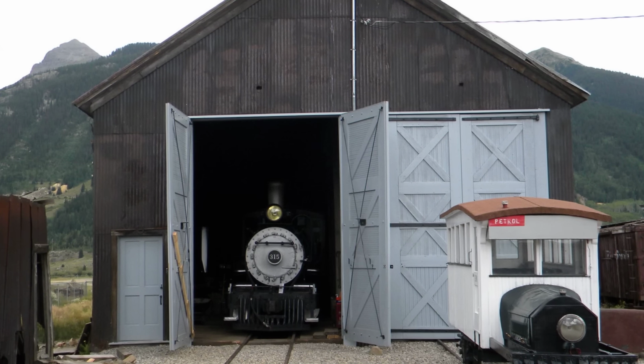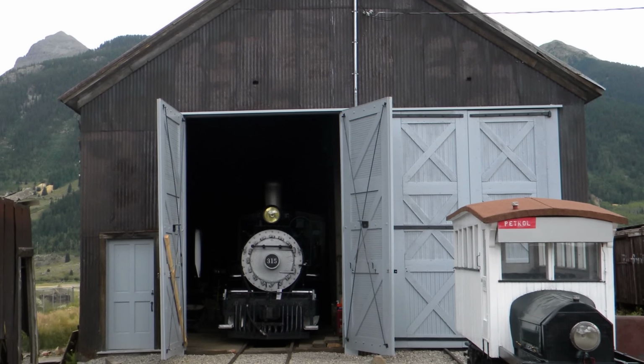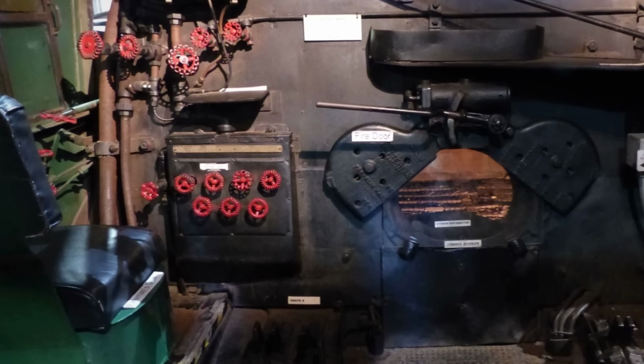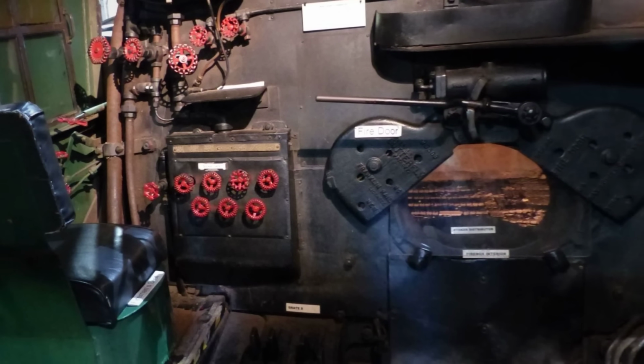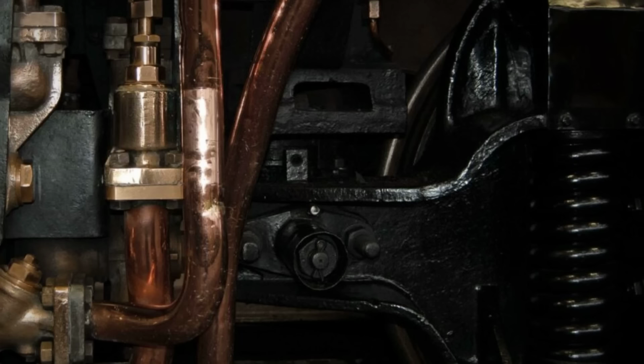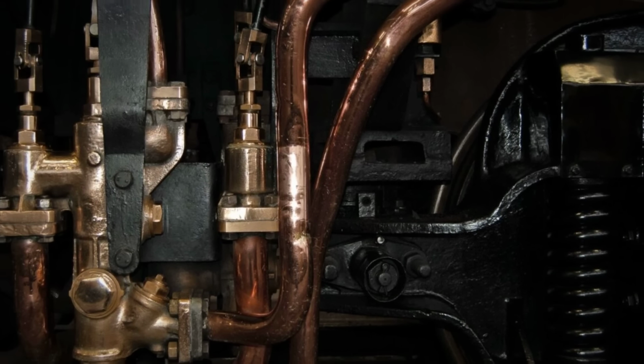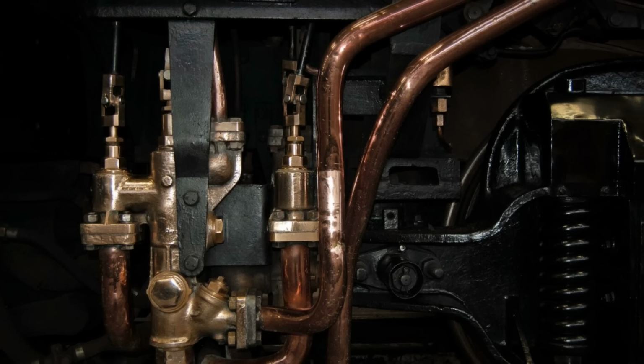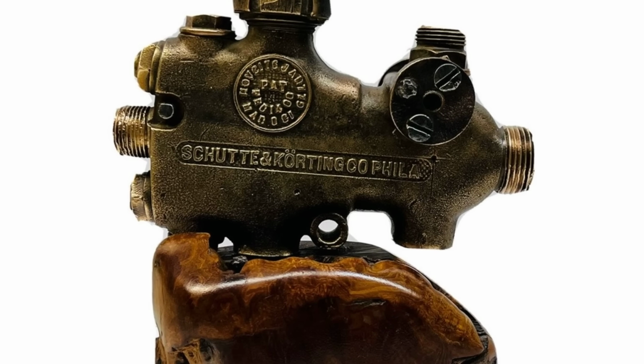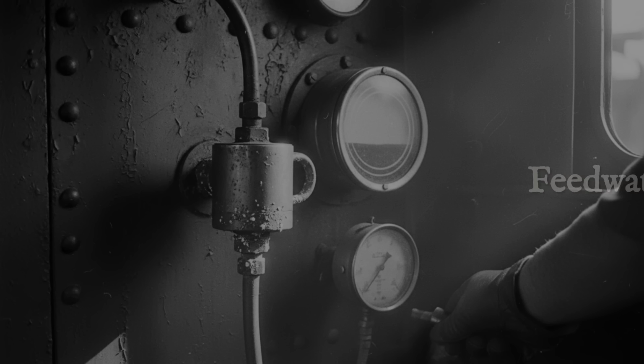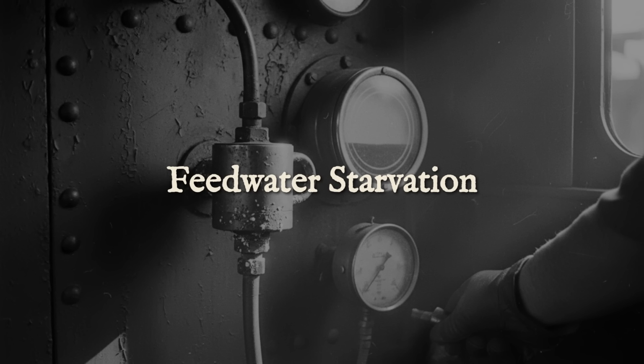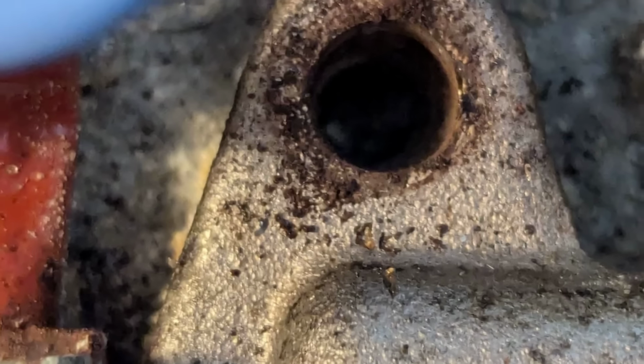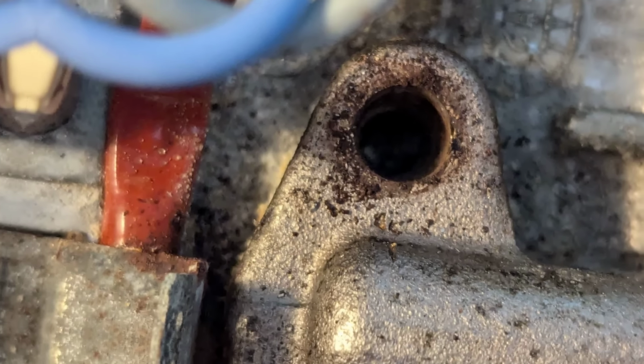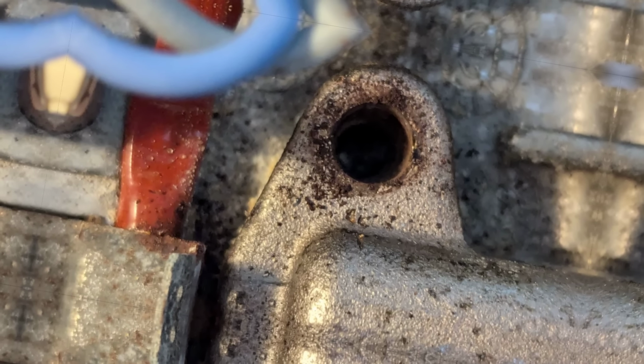A locomotive boiler is only as strong as its weakest moving part. Feed water starvation is the silent killer, an insidious sequence that begins not with a dramatic rupture, but with a trickle reduced to nothing. The injector, a device the size of a coffee mug, is all that stands between full pressure and catastrophic exposure. When it fails, by scale, by worn check valves, by a single pinhole of calcium, the flow can drop by 70% or more in minutes.